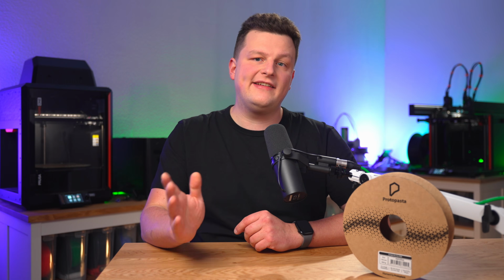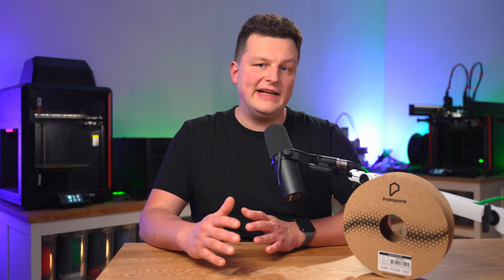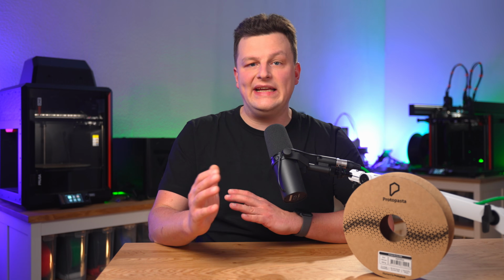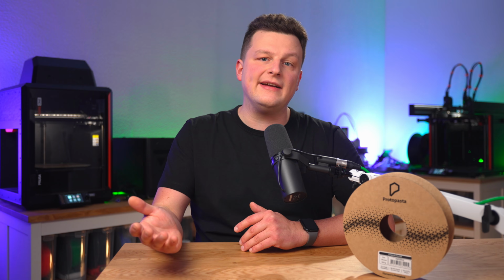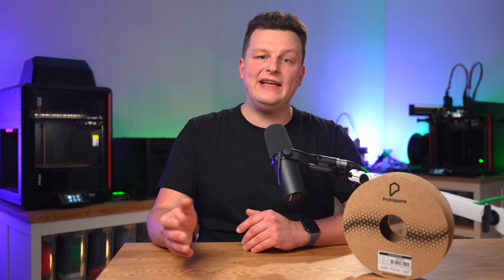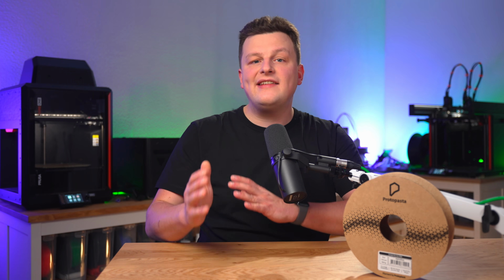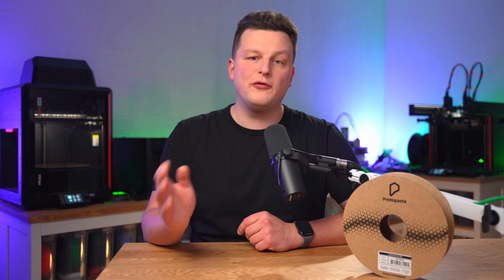The metal particles don't melt or blend with the PLA. Instead, they interrupt the internal bonding inside the plastic. The PLA can't fuse cleanly around the iron, so the parts end up with tiny weak spots throughout its structure. The print feels dense, premium and stronger at first, but mechanically it doesn't hold up and it's actually weaker.